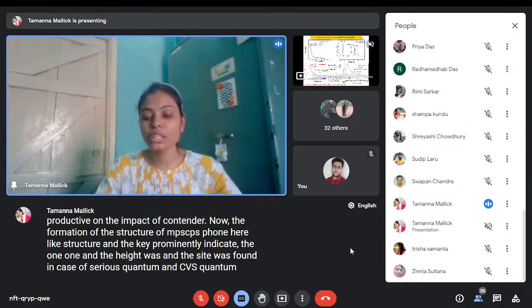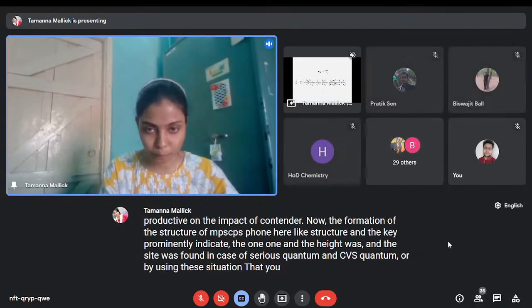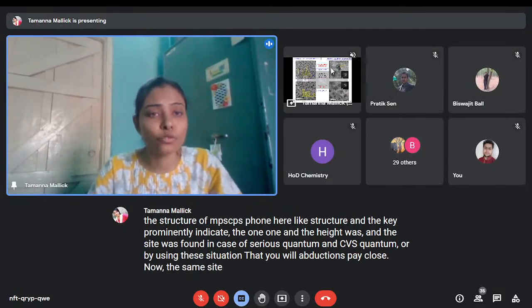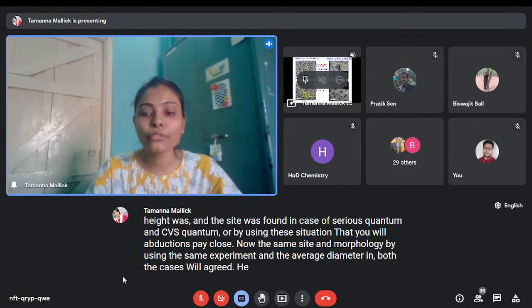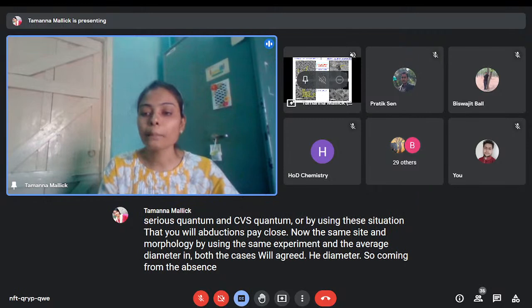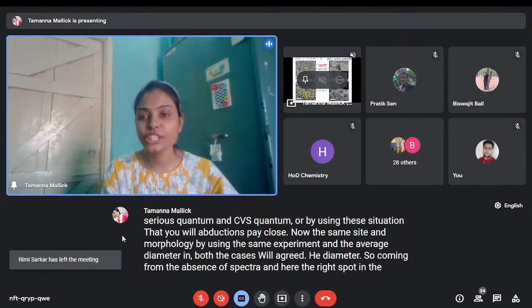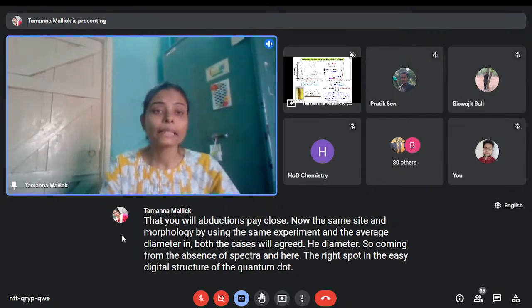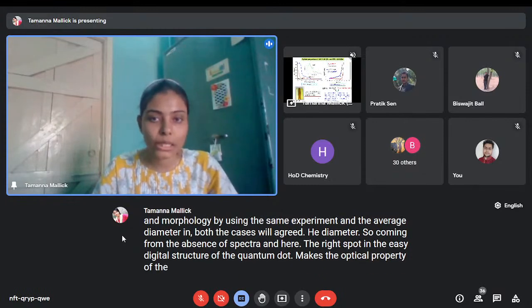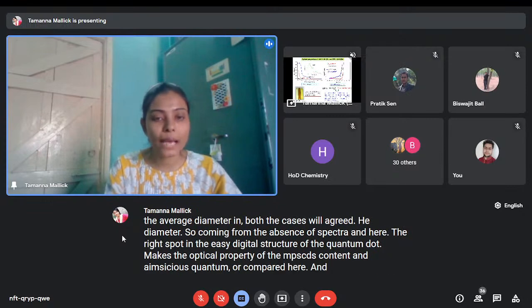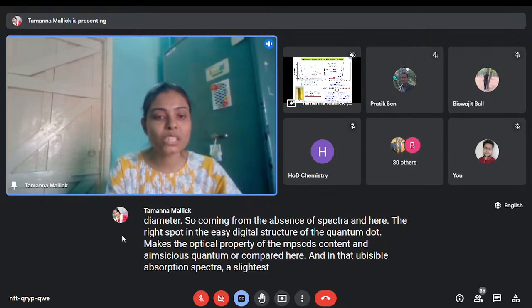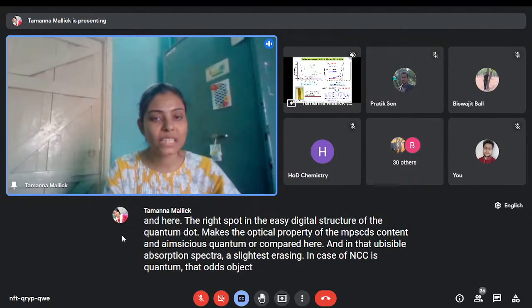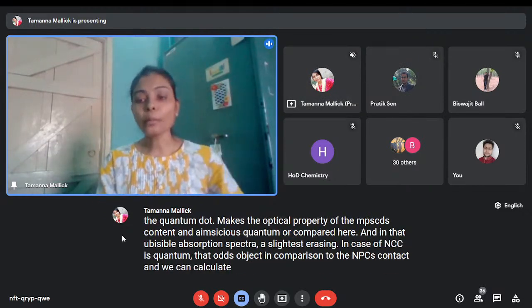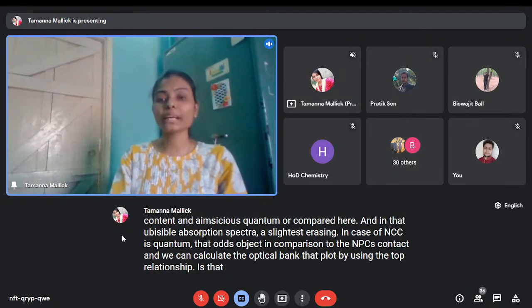was found in the case of MPA CdS quantum dot and AMC CdS quantum dot by using this equation from the UV visible absorption spectroscopy. Now the shape, size, and morphology were checked by TEM experiment, and the average diameter in both cases agreed well with the diameter from the absorption spectra. And here the bright spots in the SAED pattern indicate the crystal structure of the quantum dot. Next, the optical properties of the MPA CdS quantum dot and AMC CdS quantum dot are compared here. In the UV visible absorption spectra, a slight redshift was observed in the case of AMC CdS quantum dot in comparison to the MPA CdS quantum dot. We can calculate the optical band gap by using the Tauc relationship, and these are the corresponding values of the optical band gap.